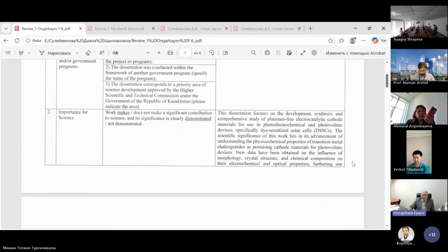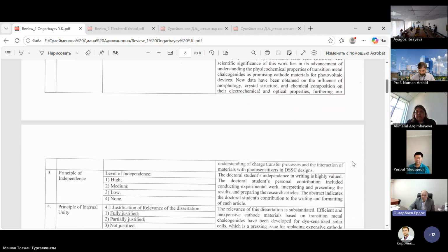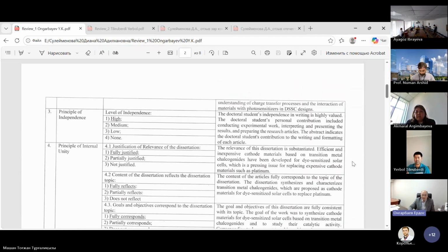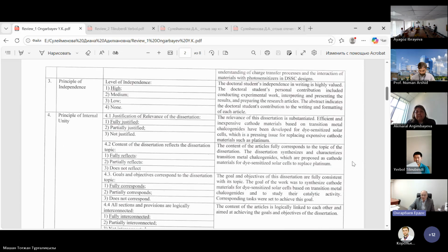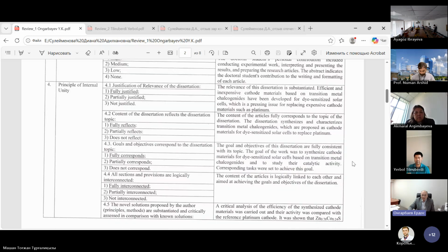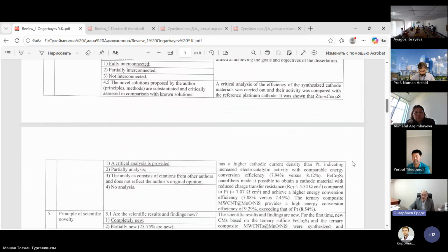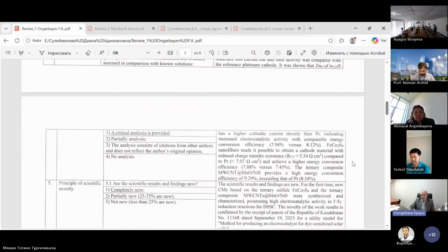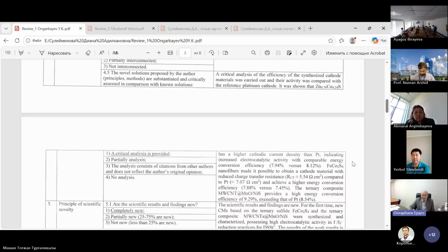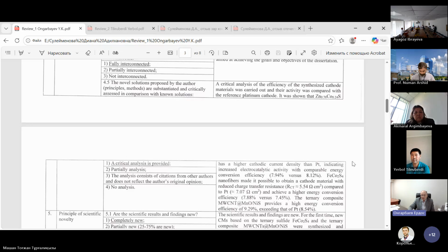Scientific results and findings: completely new. For the first time, new cathode materials based on the ternary sulfide and the ternary composite were synthesized and characterized, possessing high electrocatalytic activity in iodide reduction reactions for DSSC, and the novelty of the work results is confirmed by the receipt of the patent of the Republic of Kazakhstan number 11168, dated September 2025, for a utility model for a method for producing electrocatalysts for DSSC.